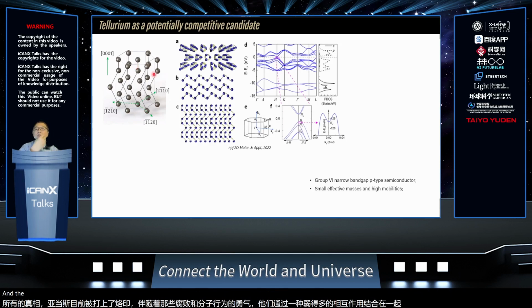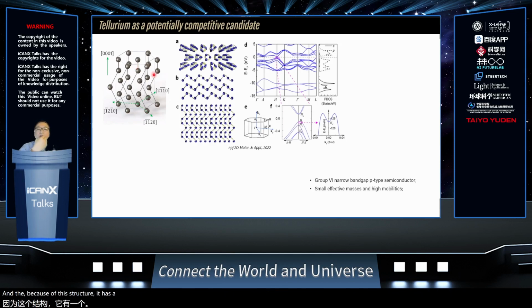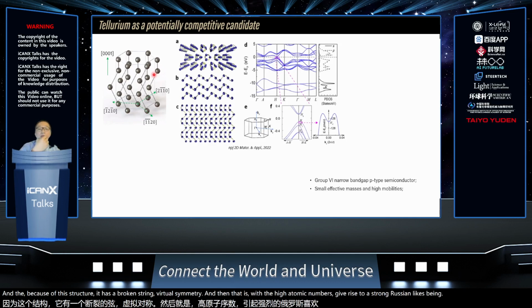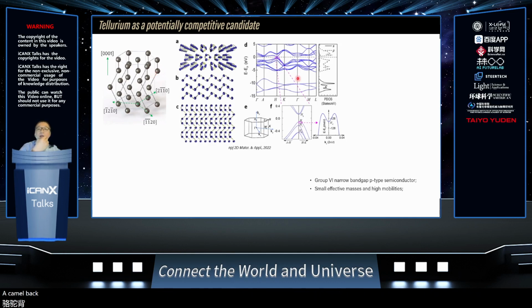And because of this structure, it has a broken spatial inversion symmetry, and that lattice with the high atomic number gives rise to a strong Rashba-like spin orbital interaction, a camelback electronic structure at the edge of the valence band, and also radial spin textures. And because of this intriguing structure, tellurium has small effective masses and also high mobilities.